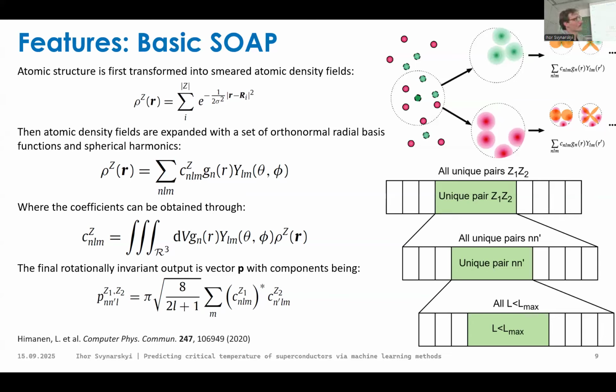It was also remarked, as Ihor correctly said, that it's a local descriptor. So it's like a descriptor of some local crystal environment. And of course, when calculating, you should take into account the images from the next cell, the supercell images. So it should be accounted for during the calculation of this density. But the question is if you take one atom and another atom from a neighboring unit cell, whether you can neglect these features or whether they actually add something. That's controlled by a hyperparameter, this cutoff distance. If I remember correctly, the cutoff distance was up to five angstroms or something, so it's like the size of the unit cell.